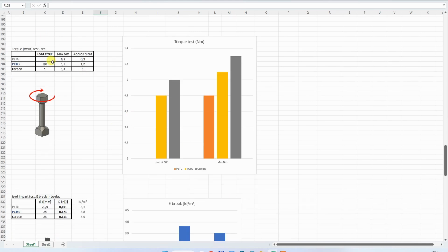On the torque test, you saw the PETG broke too early, after maybe a 40-45 degree angle, so it couldn't do the 90 degree rotation to see that load. So in this test, the carbon was the best.